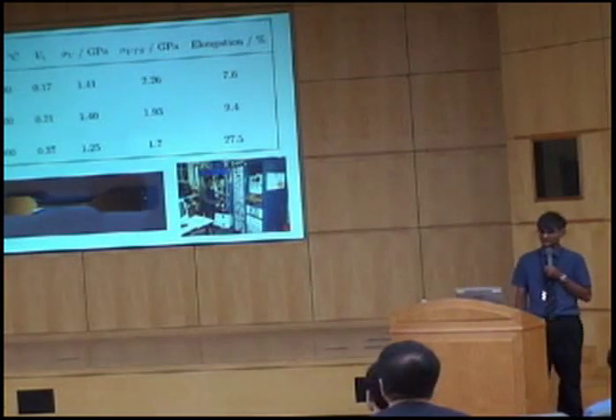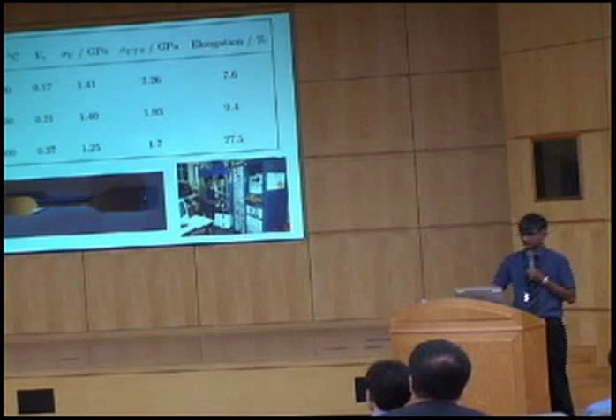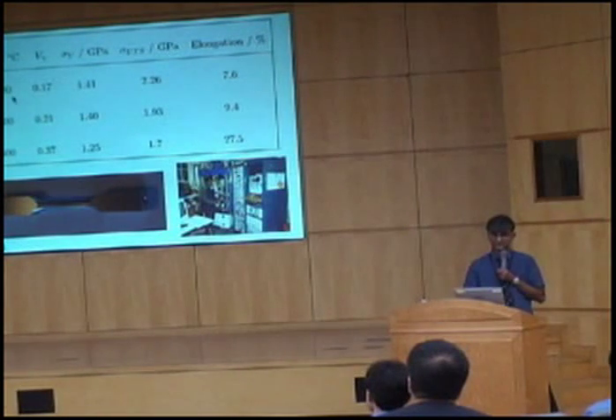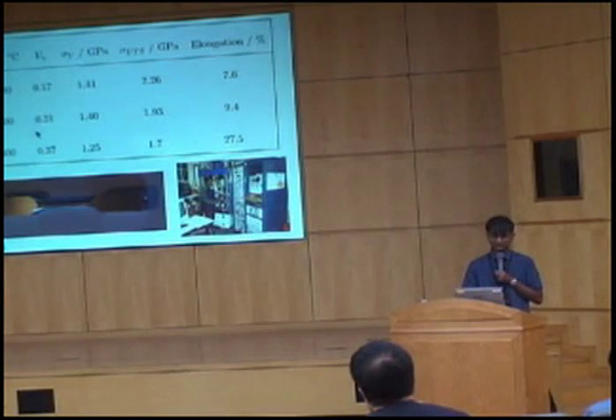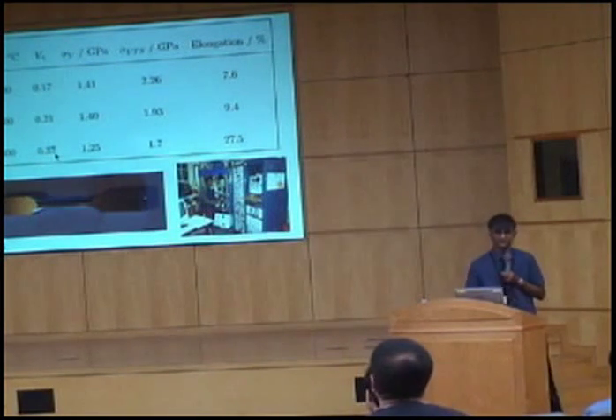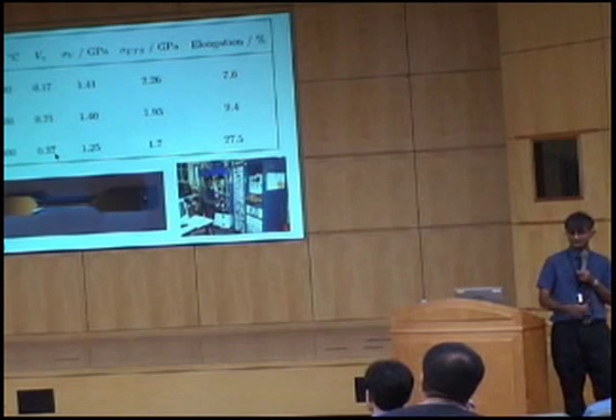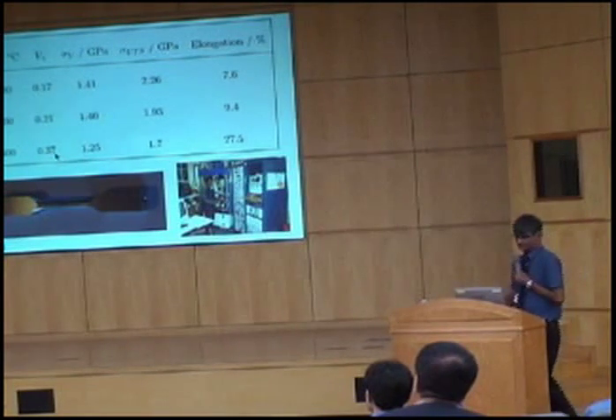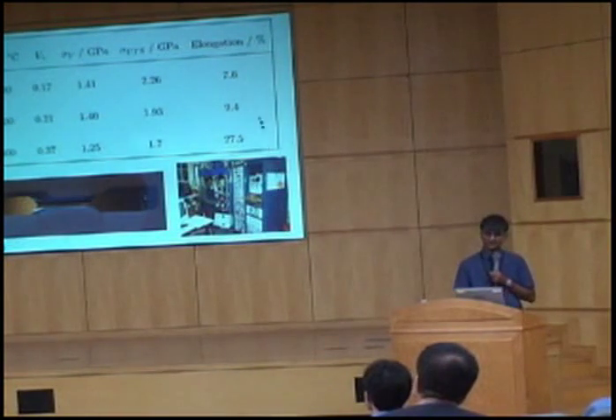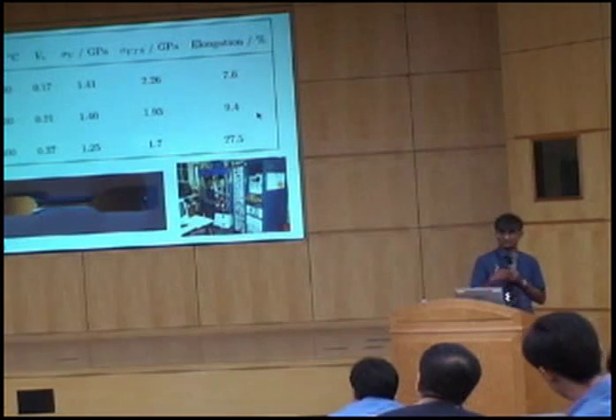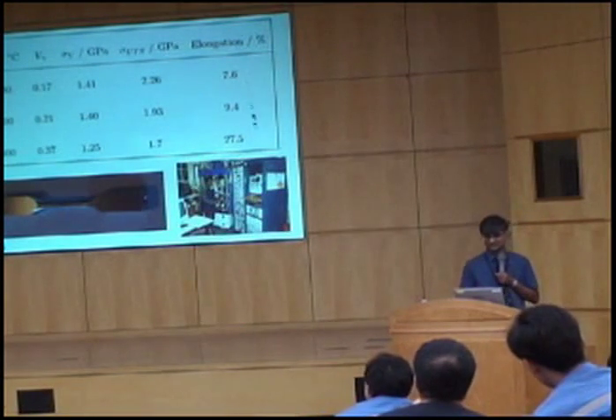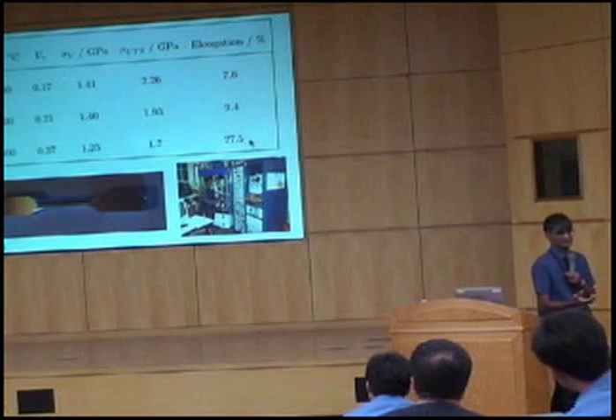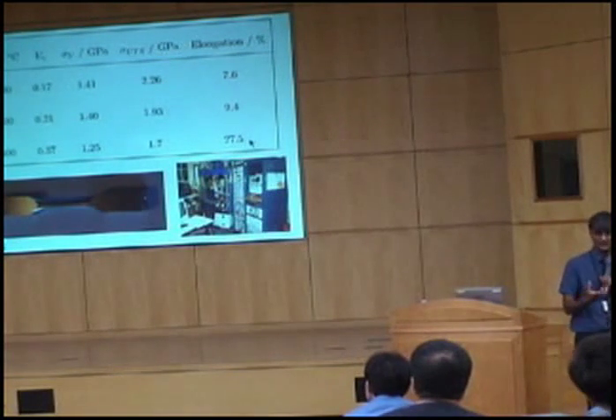Well, supposing we have three different kinds of bainitic steels. In one case, we have 17% of retained austenite, 21% and 37%. So this is just a mixture of bainitic ferrite and austenite. We see that the elongation is different. Okay, so here we have about 7%, here we have 27% of elongation. Now, why is that?